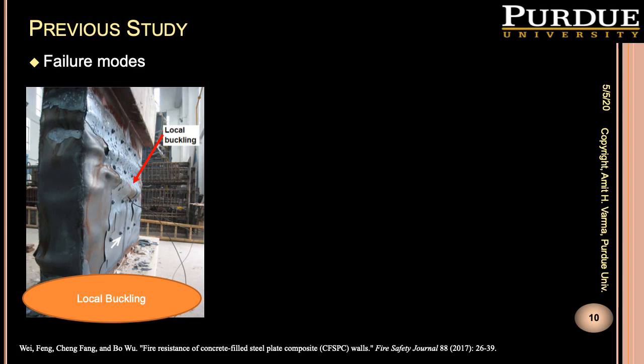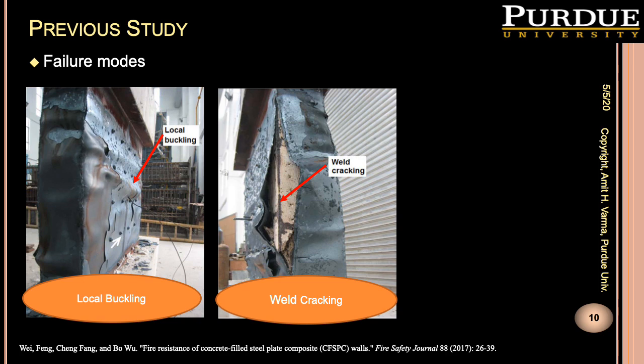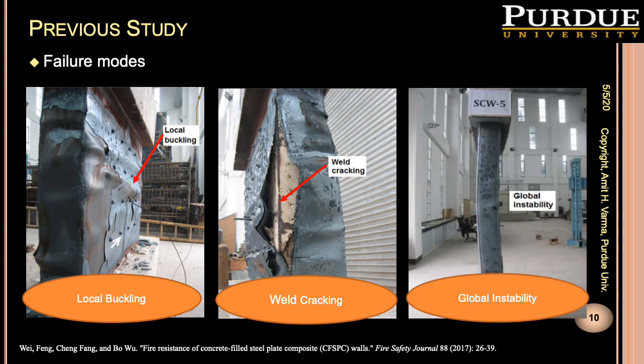Some of the failure modes that were observed during this test include, for example, local buckling. Extensive local buckling was observed in between the tie bars. This was associated with some shear stud failures in between the tie bars as well. Another failure mode that was observed was cracking of the welds at the corners between the flange plates and the web plates, the splitting failure. And another failure mode that was observed for one of the specimens was global instability, where the specimen H over TW, height over thickness, was slender enough that the specimen was undergoing overall global instability. These were some of the failure modes that were observed during the test in China.